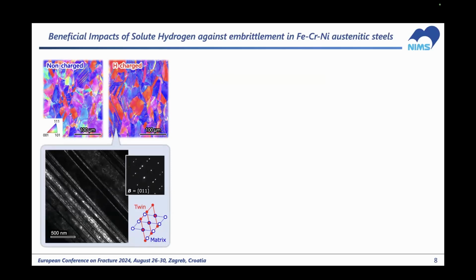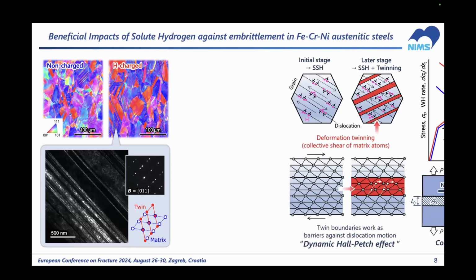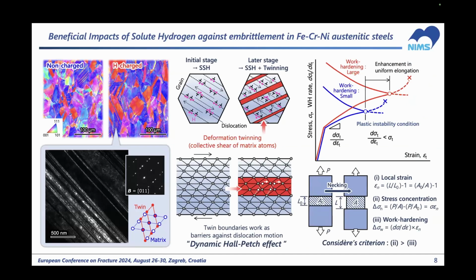And in such a later strain regime prior to necking, what we found was deformation twinning already in the non-charged specimen. But in hydrogen-charged specimens, as presented by Professor Matsumoto in the morning session, the density of deformation twins was increased by hydrogen. So hydrogen enhanced the deformation twinning at the later deformation stage. The newly created boundaries between matrix and deformation twins act as barriers against dislocation movement. So it causes the enhancement of work hardening, which in other words results in the enhanced uniform elongation because of the retardation of the plastic instabilities. So this is why hydrogen caused the improvement in the uniform and fracture elongations in the present material.